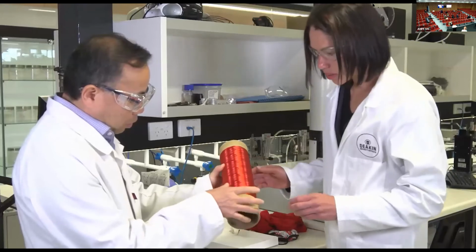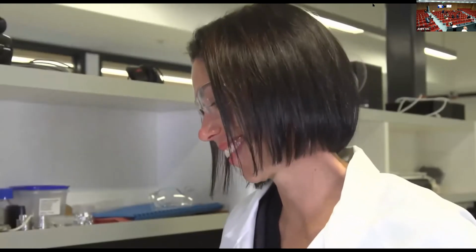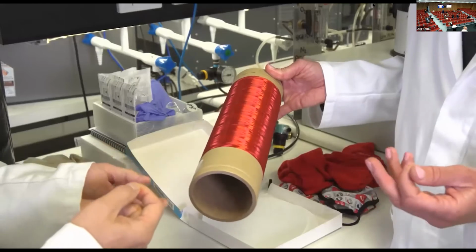Another environmental benefit is that we can retain the dye on the fibres throughout the recycling process. Dyeing and colouring are the most energy-intensive and polluting part of textile manufacture. Our novel pre-treatment process allows the fibres to retain their original dye, eliminating the need to re-dye recycled textiles.